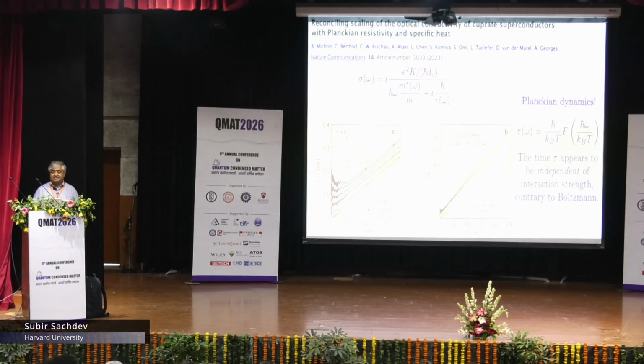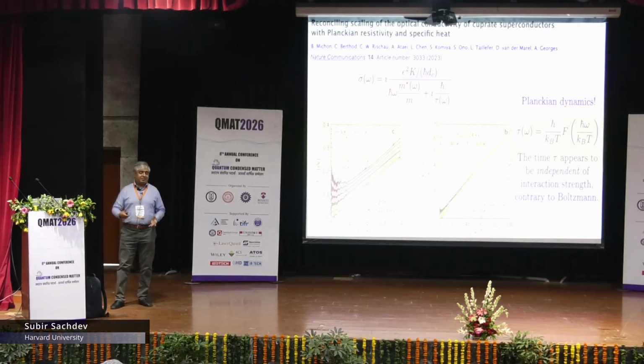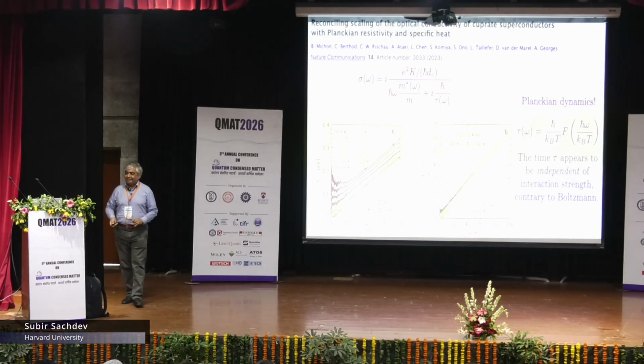Now you can fit this result to this kind of generic form, and I won't go into detail where this comes from. It's a very general form, and it gives you a measure of this collision time tau. So that was very important in the Boltzmann equation. So the collision time tau depends on frequency, and you can directly measure it. And what they found, as many theories had also indicated earlier, is this time obeys this remarkable formula, which is illustrated in this plot, that at low frequencies, where you think of f as just some number, tau is exactly the Planckian time. So you have a relaxation or collision time that doesn't depend on the strength of the interactions. This is absolutely impossible in the Boltzmann equation. In the Boltzmann equation, the collision time, as I showed you, depended on this coupling U, which is how strong the interactions are. And here, it disappears.